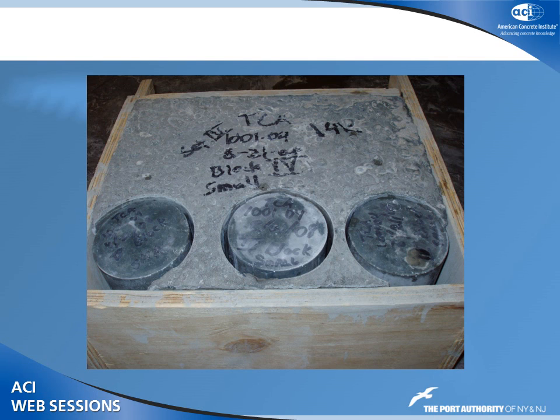And others, we also tried to mimic what we got in the field, 160-degree temperature. And we tried to get the concrete up to 160 degrees in 24 hours or 190 degrees to see what detrimental effect that would have. With the 300 pounds of cement in the mix, we couldn't do it. Okay, we could never get the temperature of the concrete to peak at 160 or 190 in 24 hours. It took about 2 days before we could get there. But anyway, I'll show you that data.